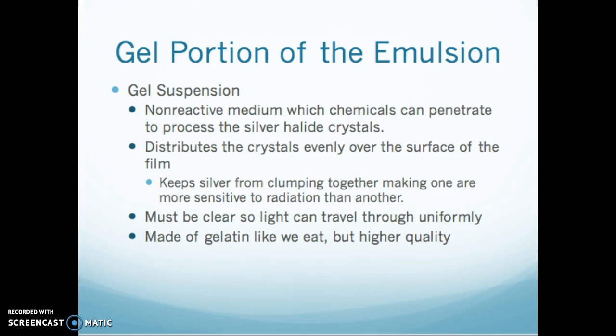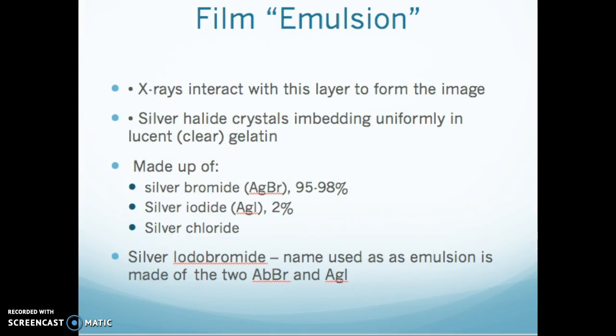So the gel suspension is a non-reactive medium which chemicals can penetrate to process the silver halide crystals. It distributes the crystals evenly over the surface of the polyester base. It keeps the silver from clumping together, which would make one area more sensitive to radiation than another, so it keeps it uniform. It must be clear so light can travel through uniformly, and it's made of gelatin like what we eat, but a higher quality. X-rays interact with this layer to form the image.